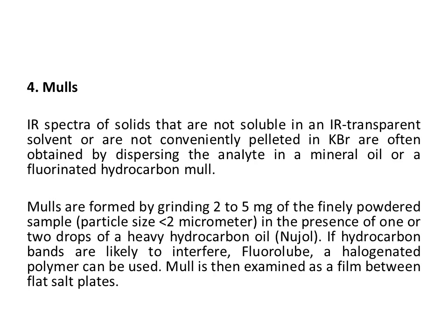Remember, when you do the analysis in solid state or in a dispersion, you have to reduce the particle size below the wavelength of incident radiation, so that scattering will be absent. So the mulling technique also is a dispersion technique. You have to finely grind your material so that scattering is minimum. In mulling, you mix your compound along with a heavy hydrocarbon oil, also called Nujol. Hydrocarbon means compounds containing only carbon and hydrogen. It's a heavy oil.